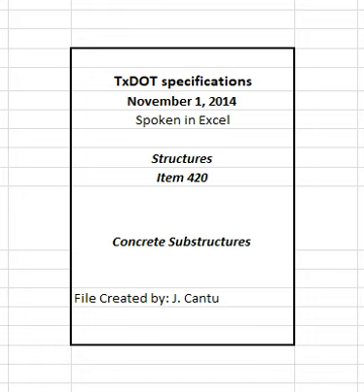Adequately illuminate the entire placement site as approved when mixing, placing, and finishing concrete in non-daylight hours. Furnish adequate shelter to protect the concrete against damage from rainfall or freezing temperatures as outlined in this item if changes in weather conditions require protective measures after work starts. Continue operations during rainfall only if approved. Use protective coverings for the material stockpiles. Cover aggregate stockpiles only to the extent necessary to control the moisture conditions in the aggregates. Allow at least one curing day after the concrete has achieved initial set before placing strain on projecting reinforcement to prevent damage to the concrete.